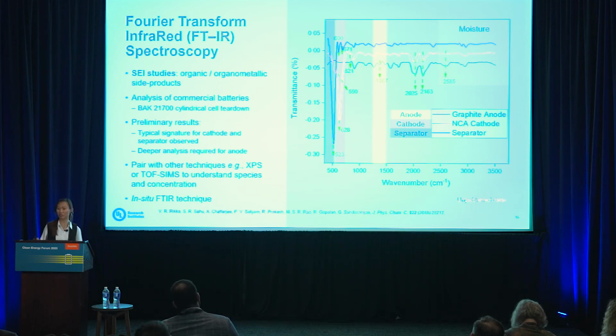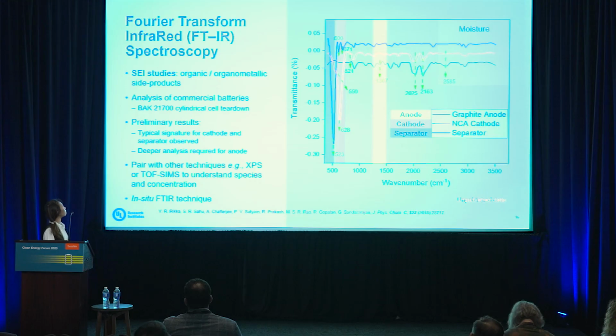We are in the process of trying to ensure that the equipment is well set up, and that any moisture or background subtraction that we do is better. So pardon how it looks right now, but we are trying to make sure whether this is because of the equipment or because of our samples. But we can still have some preliminary results. We see some signatures from the cathode and the separator, as highlighted in red and blue here. That's pretty much the signatures that we observe. However, a deeper analysis is required for the anode.